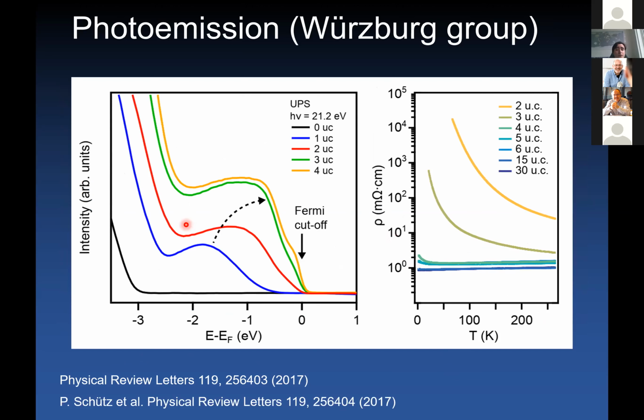In parallel with our study, also the Würzburg group from our chairman Ralph Claessen was interested in this problem, and they have provided beautiful photoemission data that is published here, where they directly saw the transition from a conducting state to a correlated insulating state by mapping the whole Fermi surface of the system. And this is very nicely consistent with our transport data and our magnetotransport.